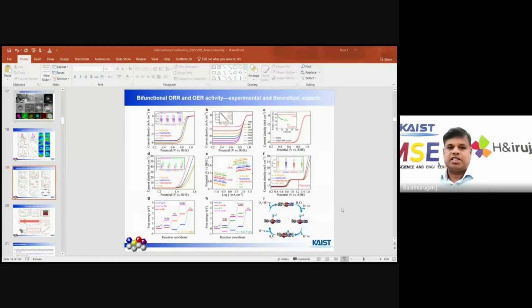After confirming the structural investigations, we do the ORR performance, the oxygen reduction reaction. When we do the oxygen reduction reaction, we have to look at the onset potential, because towards the positive, the onset potential is very high compared to the commercial platinum carbon. We have to compare with the commercial platinum, and our optimal catalyst gets a higher onset potential and a higher half-wave potential. Half-wave potential is the middle point between these two. Half-wave potential and onset potential are very important. With higher onset and half-wave potential, we can claim higher ORR performance compared to the commercial as well as other counterparts.